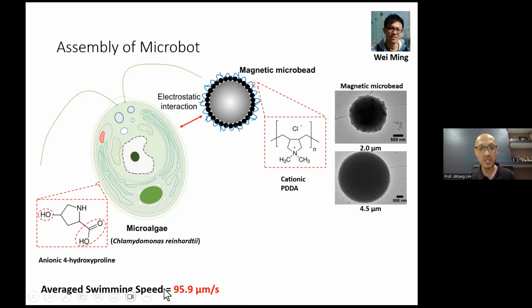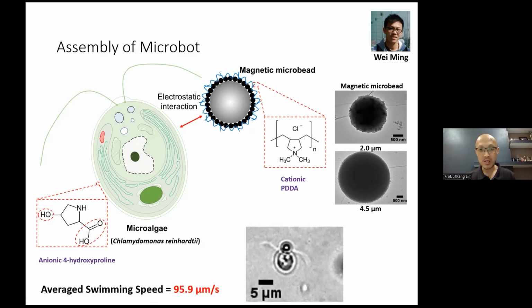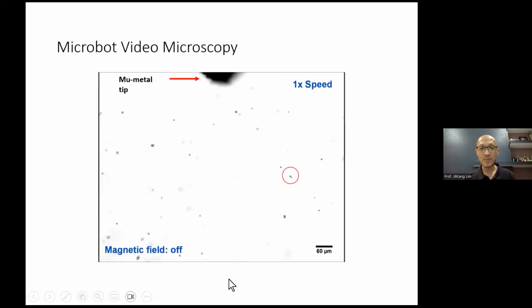Since they have flagella, they can swim, right? So it swims at around 100 micrometers per second. And we're using two different sizes of microbeads. So eventually we try to construct a microbot construct, something like this. These are the optical micrograph images of the microbot, in which we can see one part is the magnetic bead and the other part is the microalgae. So we name the whole construct a microbot.